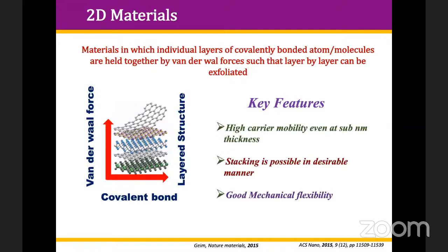As far as 3D materials are concerned, like silicon and 3-5 compounds, which are conventional semiconductor materials, in the Z direction, a covalent bond also exists, whereas in this case, only van der Waals forces exist. So that's the basic difference between conventional 3-dimensional material and 2-dimensional material. Also, if you want to make nanomaterials from 3D materials and reduce the thickness so that a monolayer or bilayer can be achieved, that is possible, but because of the covalent bond in the Z direction, there is the possibility of dangling bonds, which are not present in the case of 2D materials. That's the advantage of 2D material.